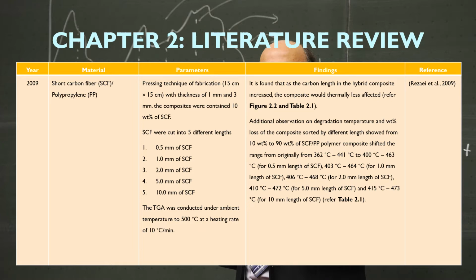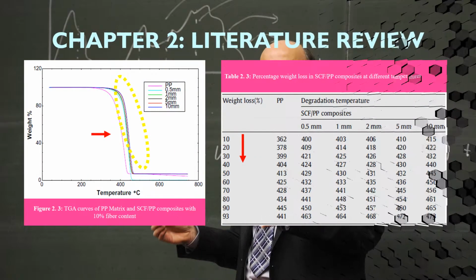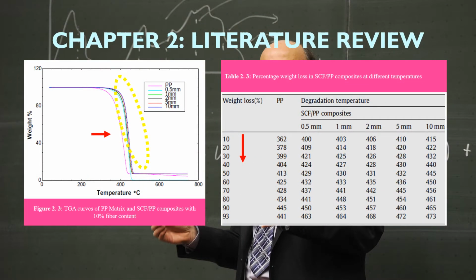Other than that, from Rezaei and his colleagues on the TGA result of polypropylene and short carbon fiber polymer composite, in his findings, it was found that first, as the carbon fiber length in the hybrid composite increases, the composite is thermally less affected. This can be referred to in figure 2.2 and table 2.1.